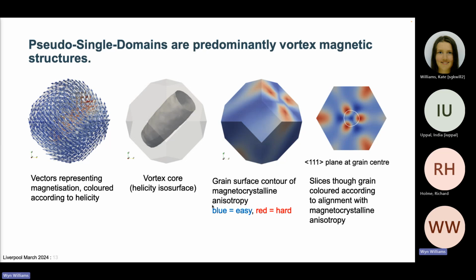I'm going to run through just a few slides that show the variation of magnetic structure as a function of grain size. This is actually work of Les here, who built this really fabulous, completely independent micromagnetic model as a PhD student. And these are the results. This particular micromagnetic code was good for very large models, going up to about 3 million elements or something more. But what it allowed us to do is to trace the development of domain structure as a function of grain size right up to multi-domain grains.